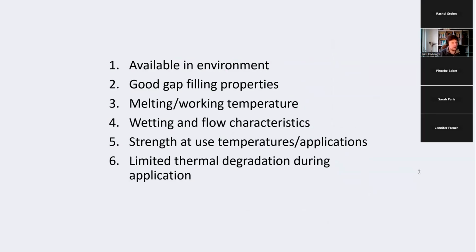So to get back here to the criteria, points 1 and 2 are both satisfied for both of the adhesives. They're both available in the environment about equally. They both are hot melts and have good gap filling properties. Point 3 is given to birch bark tar because the working temperature is high enough so as not to be too soft during regular use, but low enough not to burn you when you apply it. Point 4 also goes to birch bark tar. It remains firm so as not to flow out of the joint.